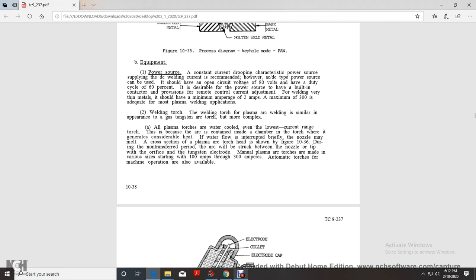The welding torch for plasma arc welding is similar in appearance to the gas tungsten arc torch, but much more complex. All plasma torches are water cooled, even in the lowest current range, because the arc is contained inside the chamber of the torch, where considerable heat is generated. Without water flow, the nozzle may melt. A cross-sectional plasma arc torch is shown in figure 1036. During the non-transferred period, the arc is struck between the nozzle and the tungsten electrode tip in the orifice.